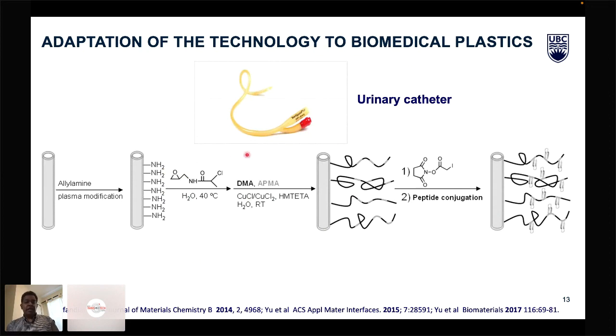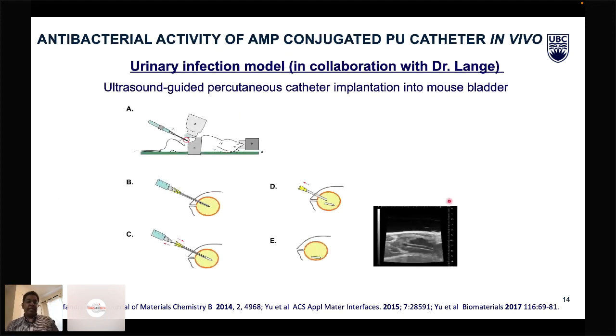modification. So we adapted this method to a urinary catheter. Earlier it was a titanium implant, and here we have a plastic implant. For the urinary catheter, we utilized a plasma modification followed by surface initiated polymerization to generate this peptide coated urinary catheter, and then we further utilized a urinary tract infection model in association with the